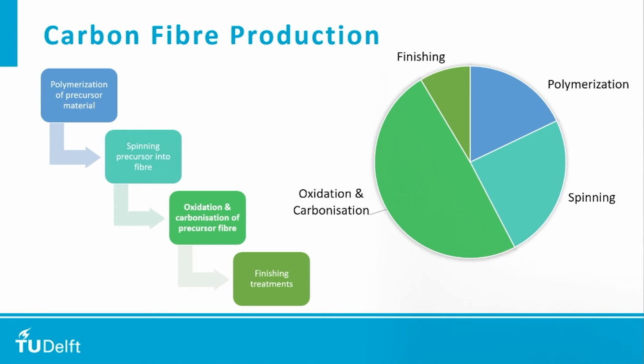The oxidation and carbonization step is the most energy-intensive, amounting to approximately 50% of the total energy consumed in the manufacturing of the carbon fibers. It is followed by the spinning process, which consumes approximately 25% of the total energy.